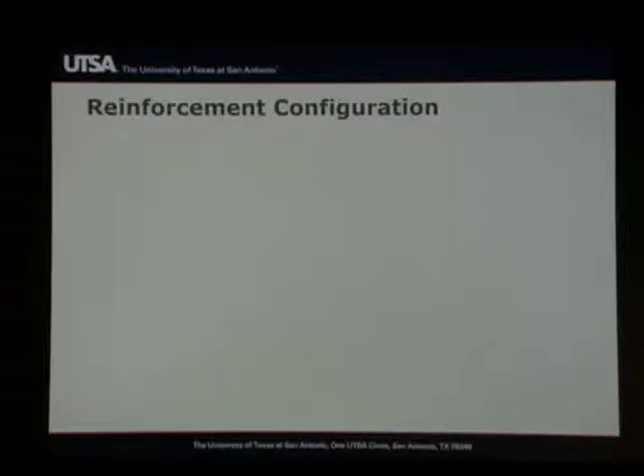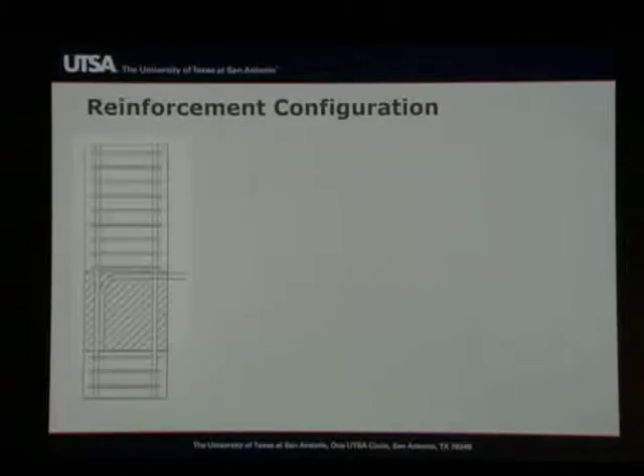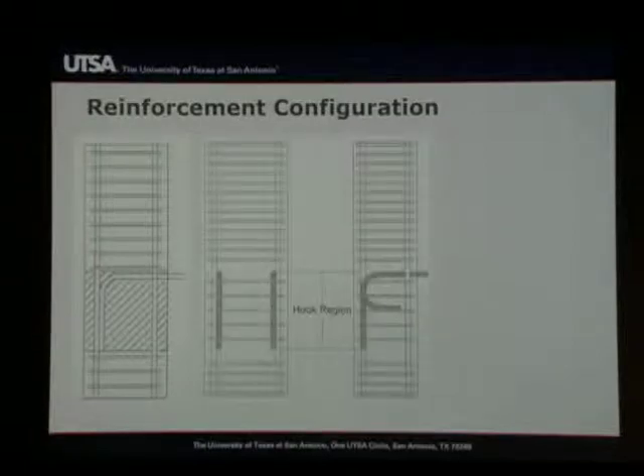So we tested several configurations of specimens. I'm going to give you a rundown of the most meaningful. The first one we did is a specimen in which there was no reinforcement within the joint region, which has always troubled me a little bit, because if you think of those struts from the previous diagram, there's a strut that goes up from the hook region, and that strut is going to cross reinforcement. But that's kind of unavoidable in the sense that we really need to avoid a shear failure in that region, and we wouldn't be able to avoid that if we leave the shear reinforcement out. But in the lower part, nonetheless, we don't have any reinforcement, and that strut will flow to the support without any help from transverse reinforcement. So that's one of the configurations that we use.